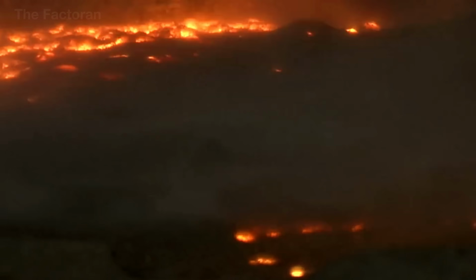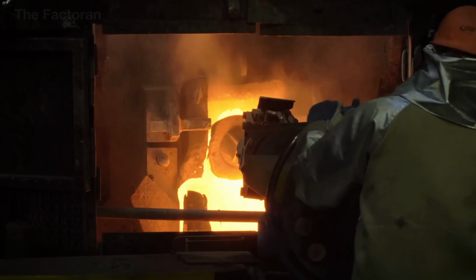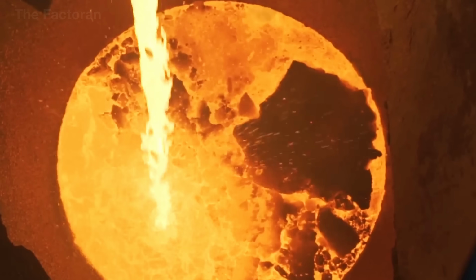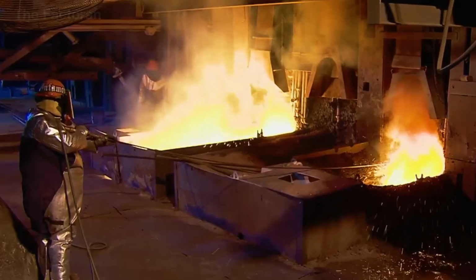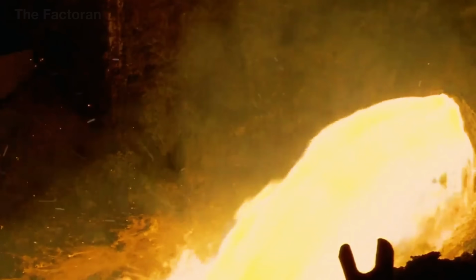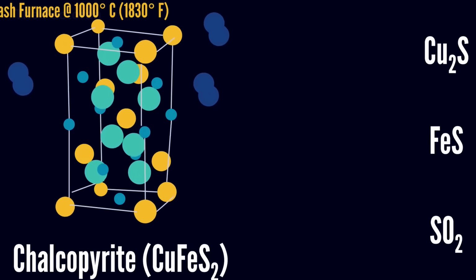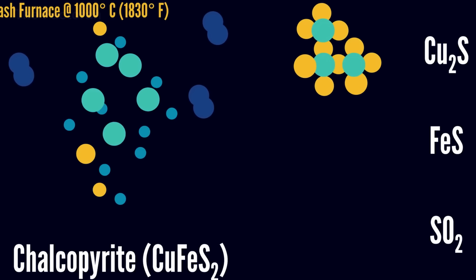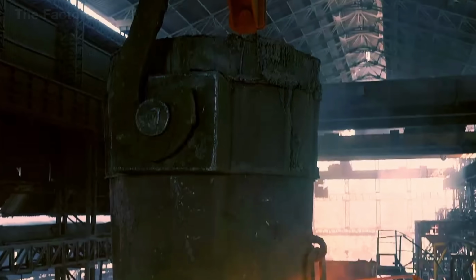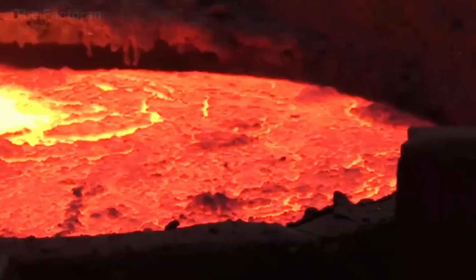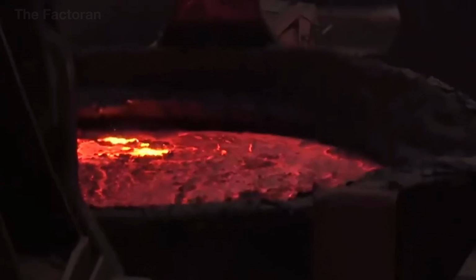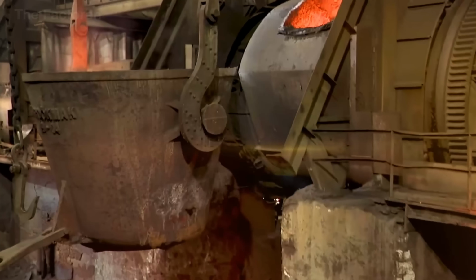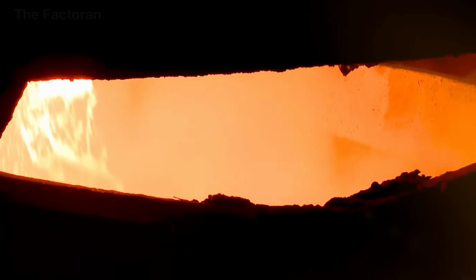massive industrial furnaces that can stretch dozens of meters and reach temperatures up to 1,200 degrees Celsius, hotter than volcanic lava. Inside, the material is heated together with silica and other additives, which help remove impurities. Elements like iron react with the silica to form a lighter, molten slag that floats to the surface, much like foam on a boiling pot of soup, while the denser molten copper settles at the bottom, dark and heavy like thick syrup. The result is what's known as blister copper, named for its rough, blistered surface as it solidifies.